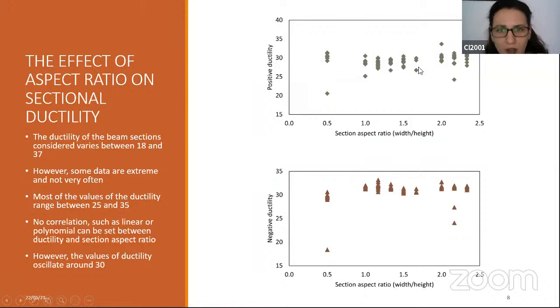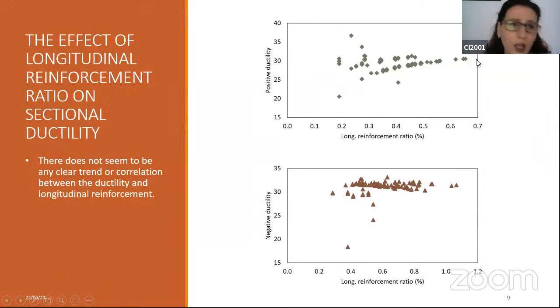The values of ductility oscillate around 30. There is this range of 25 to 35 where most of the ductility values are, let's say, concentrated, but there are also outlier values as low as 20 or even lower and as high as almost 37. So from the aspect ratio versus sectional ductility, we were not able to define a clear correlation between these two parameters. And similarly, when we obtained the relationship between the ductility and the reinforcement, we were not able to observe any clear correlation. For lower reinforcement ratios, there was quite a scatter, as we can see here in the data points, and the scatter became less